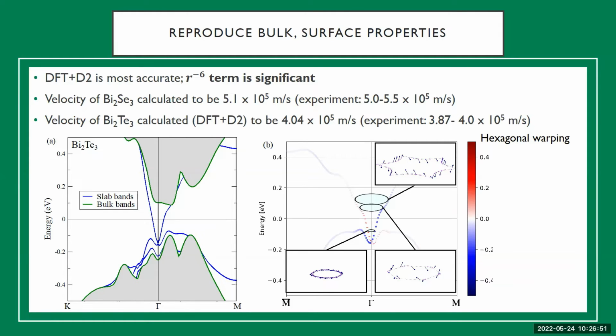If you remember the slide at the beginning where I showed the helical structure, close to the Dirac point, we find that the spins are all in the plane. So we just have a circular dispersion, which is the bottom left panel in panel B. But as you increase the energy, the dispersion becomes hexagonal, and then it becomes almost star-shaped. And the blue arrows, which represent the spins, start pointing out of the plane. So the spin momentum locking changes as you go away from the Dirac point.